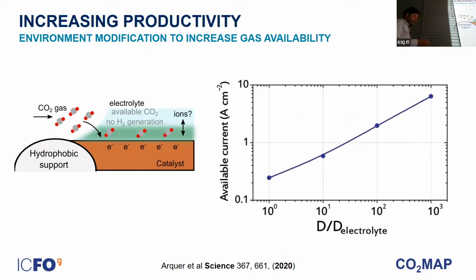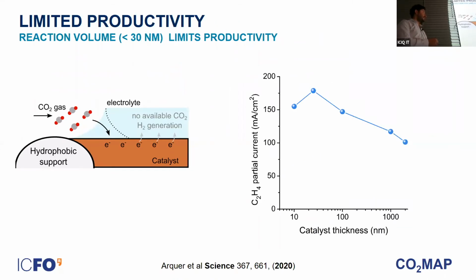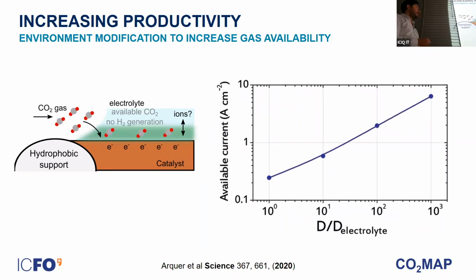So we thought, okay, what if we modify the substrate of the catalyst in such a way we could make more CO2 available across the reaction interface? Just to remind you, in this case, we learned that only the first tens of nanometers are performing the reaction. So only 10 to 20 nanometers are useful. What if we could extend this reaction interface much into the catalyst? So we began modeling what will happen if you just increase the availability of CO2, for example, by considering the diffusion coefficient of CO2 on top of the surface of the catalyst. You can see just by increasing this number, you could increase the available current within the ampere regime, so by orders of magnitude.